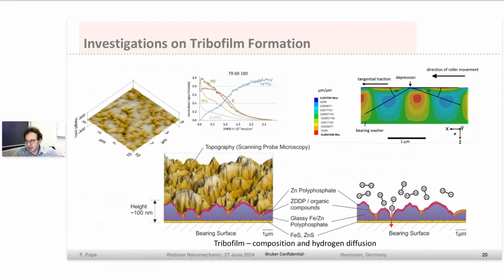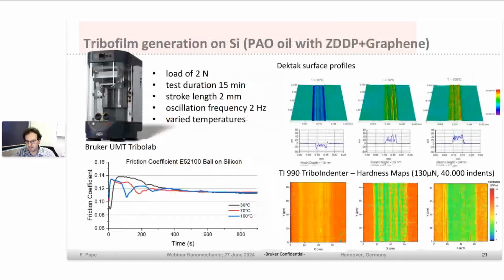What we can do with all this data is that we can use it for our simulation models. One example is shown here, that we applied to our simulation the surface roughness from the SPM images and also some local friction coefficient. In the simulation for the bearing washers, to know about the crack opening regarding the white etching cracks, and also to understand how hydrogen can get into the steel regarding this specific surface and voids that can occur in this kind of surface that we also detected for specific samples. And we are still going on with this kind of measurements.